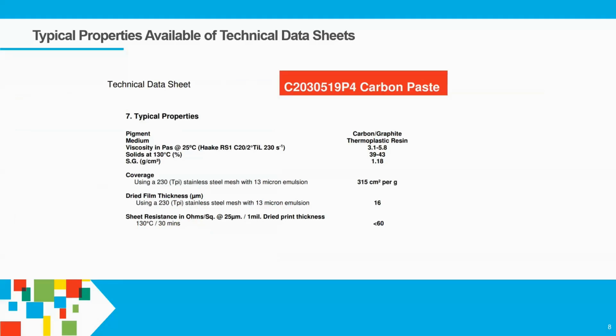So typically when people pick a material, they normally look at the technical data sheet. This is one of our technical data sheets. It's quite representative of most companies and how they present their data. You have your typical properties: pigment type, viscosity, solids, all good for the screen printing process, the coverage, dry film thickness, and other things about curing, etc. You will always see here sheet resistance, and it's normally presented in ohms per square, normalized to 25 microns.